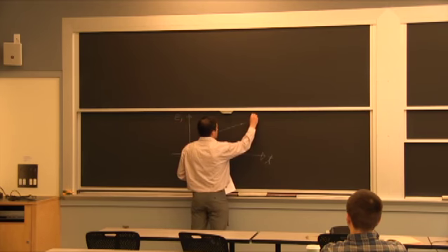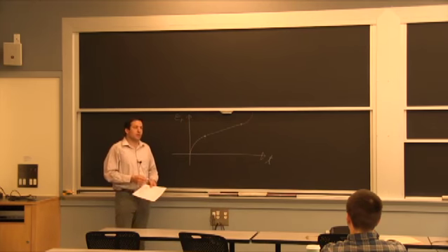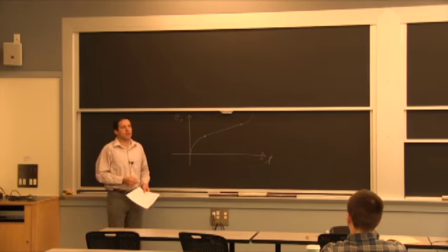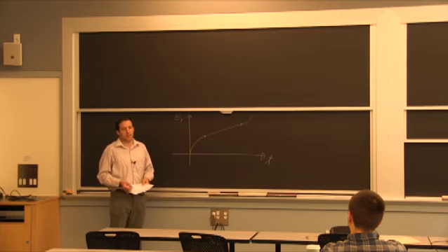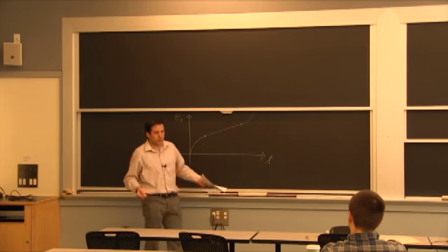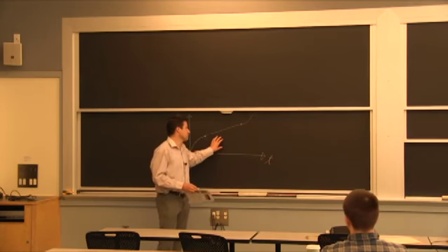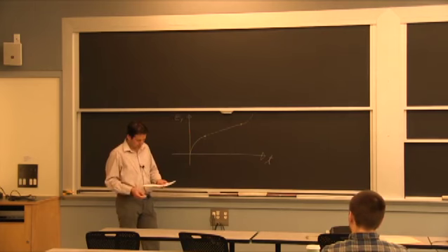Eventually, you reach the third regime where now you accelerate, and this could be due to a number of things. Microvoids is a common source when you reach a certain amount of plasticity, where you had little inclusion imperfections. You have voids that are going to start to grow to a significant size, start to coalesce together, and then you are less resisting to the deformation. Eventually you crack and fracture.